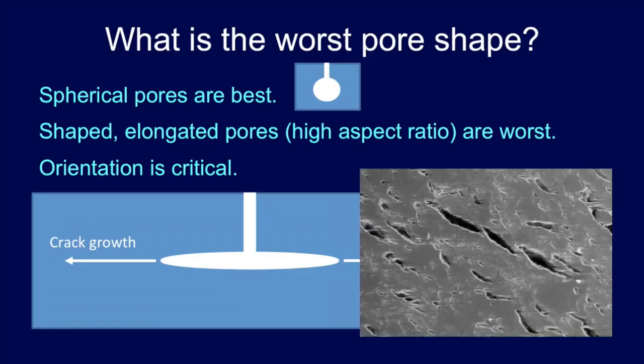These are elongated pores in a terracotta body — awesome for failure. The problem is their orientation. The material was pressed into a mold, so these pores are all now parallel to the surface. That means your potential for spalling is excellent. It will chip that clay off because it gets water in there and ratchets those pores open.